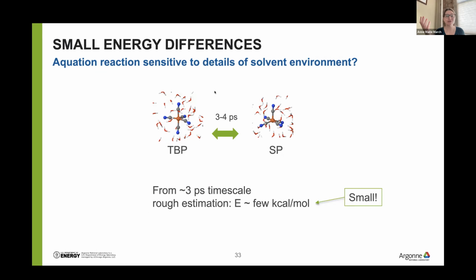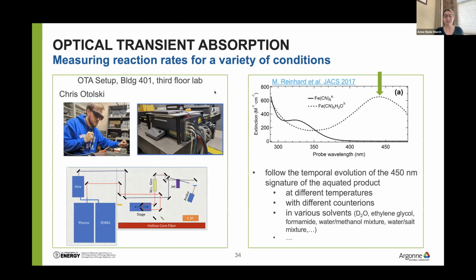Okay, so this 3 to 4 picosecond time scale for this fluxional behavior implies a very small energy difference between these geometries. A rough estimate is a few kcal per mole. This is really small, and so this got us thinking this whole process must be really sensitive to the details of the solvent environment. And we were intrigued by this, and we wanted to investigate this. So we can't just spend all our time at the beamline consuming all the beam time. So we had to have an offline means of investigating this.